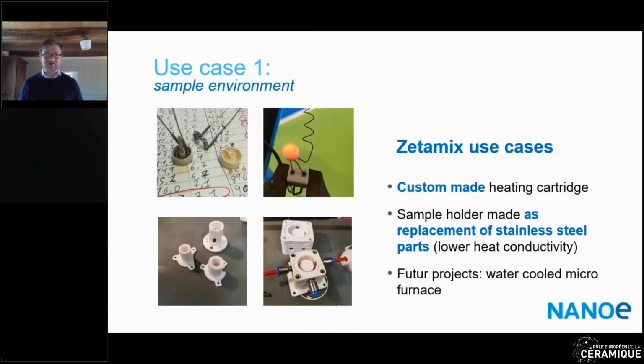So what does the ESRF do with our technology? They make, for the moment, mainly 3 parts, even though some others are in progress at the moment. Some simple parts, such as heating cartridge, it's 2 pictures on the top, where you can see a ceramic part which is 3D printed, and heating elements. Some sample holders, which are also relatively simple. It's on the lowest side and on the left side, and then they have a future project which is a bit more complex, about making some water-cooled micro furnaces. So a furnace where you can go up to 1200 degrees C inside, but the wall would still be at room temperature because it is cooled by a water circuit on the outside.